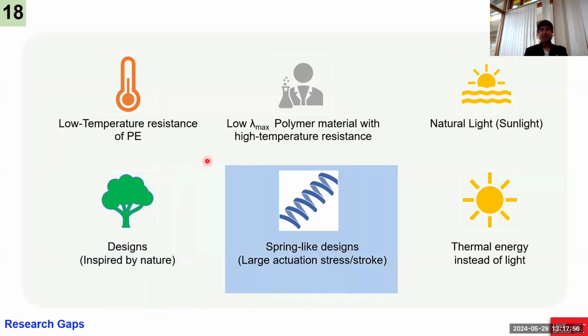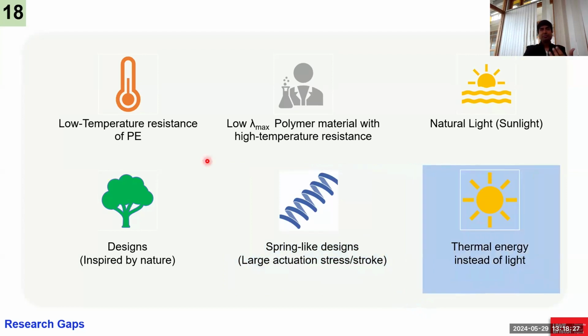Also, since our work is based on higher actuation stress and the actuation strain is limited, we can think about designs where we use multi-filament threads rather than a monofilament or a film, and then twist them together to get an addition of all these strains, maybe a spring-like design, to get a large actuation stress and stroke. And because the heat is generated within the polymeric film, which actually creates these actuations, we can also generate the same phenomena using thermal energy instead of light. But this might be limited in certain applications.